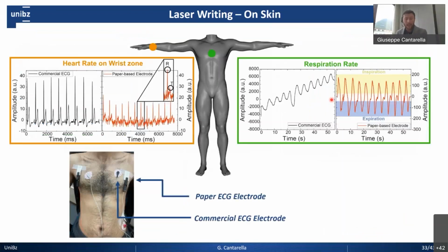We also went a step ahead, trying to see whether the biocompatibility of this paper could be even employed for on-skin application. So what we did is to compare, as you can see here in this image, the performances of the paper electrodes with standard ECG, so electrocardiogram electrodes, which are commercially available, and try to see whether, for example, there is any performance drift between one or the other one. So on the left-hand side in orange, what you see is how we could monitor the heartbeat, so the heart activity, using a triplet of electrodes. So two located on the wrist, one here, and another one on the ankle.